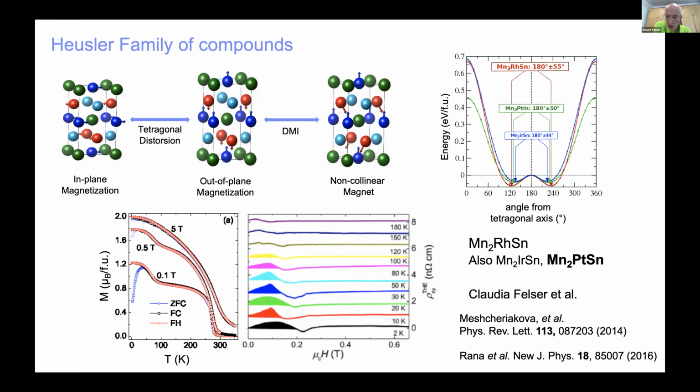magnetic textures. And this was first shown in this PRL by Meshcheriakova, and with Jürgen Kübler, they suggested that this material shows a non-collinear spin texture at low temperatures, in which the two lattices, which are ferrimagnetic, anti-parallel at high temperatures, one of them has its moments rotated, no longer anti-parallel, but at some finite angle to the other lattice. That's what they predicted. A simple non-collinear texture.